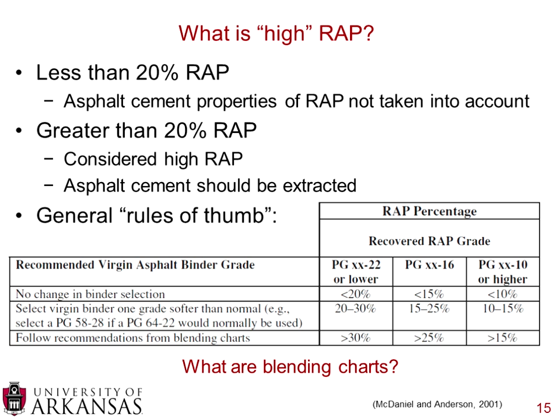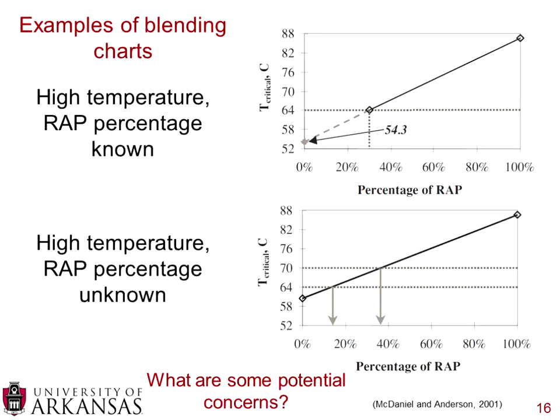Now, if you go above those levels, you need to start using the blending charts. And on the next slide, we have some examples of these blending charts. And there's two types of blending charts that they used. And they used both if you know the RAP percentage and if you do not know the RAP percentage. So on the top here, if you're looking at just the high temperature binder grade and you know the RAP percentage is known, you can go from the x-axis here. I'm going to change that to a different color so you can see it.